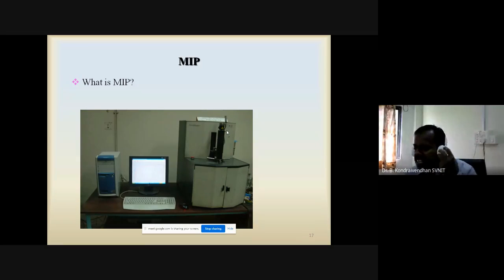There is a reduction in the mercury level, and that will be indicated by the attached Porowin software. That is how we can determine the pore sizes of the particular sample, and we can also determine the porosity. In the MIP there are 3 pressure stations available: 2 low pressure stations and 1 high pressure station. In the low pressure station we apply a pressure up to 50 psi, and there we get one cumulative intruded volume versus pressure curve.